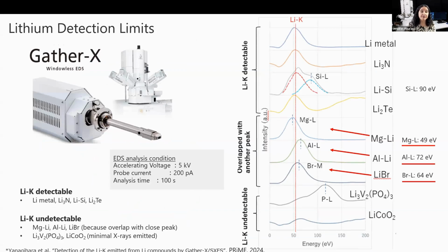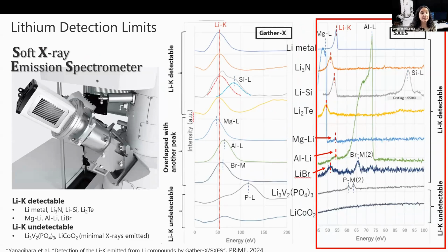So remember this graph that showed the detection limits of the Gather-X in relation to battery materials where we could not separate out the lithium peak with the magnesium, aluminum, or bromine? So here are the spectra from these same samples, now also taken with this VUV version of the SXES. The x-axis is more zoomed in. It's only showing half of the x-axis in the Gather-X data.